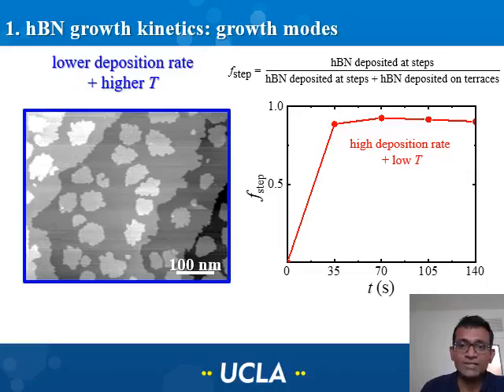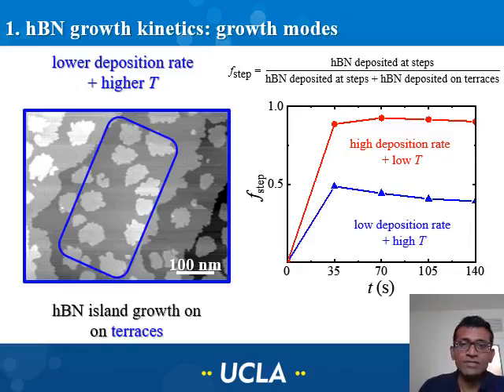seems to saturate with increasing time. Now let's see what happens when we change the deposition conditions. In this case, the step coverage saturates at 0.5, implying there are nearly equal rates of deposition occurring at the step edges and on terraces.